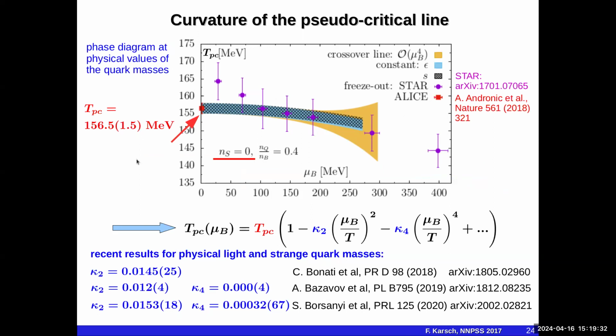So that has been done some time ago already for values of quark masses that correspond to the physical case, and we know that starting at the pseudocritical temperature, varying the baryon chemical potentials and calculating the shift in the pseudocritical temperature, the variation of the pseudocritical temperatures is rather weak, characterized by a small value of the curvature coefficient kappa, and the next correction to that, the kappa 4, at present is actually found to be 0 within errors. So what I want to do is extend this calculation to smaller values of the quark masses and then extract the corresponding curvature coefficients for smaller values of the quark masses so that we arrive at the chiral limit eventually.